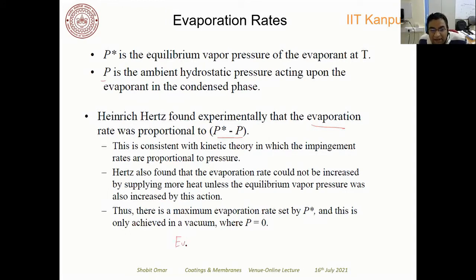So the evaporation flux is dependent on P star minus P. Okay, so if you have a vacuum, then this P, that hydrostatic pressure, is going to be zero. Then you will have the maximum amount of evaporating flux. So that is the idea: to create a vacuum inside the chamber to enhance the evaporation flux from the material, so that the condensed phase gets evaporated into the vapor phase, and then that can be easily deposited on the substrate.